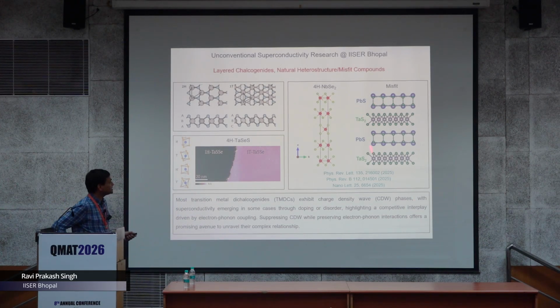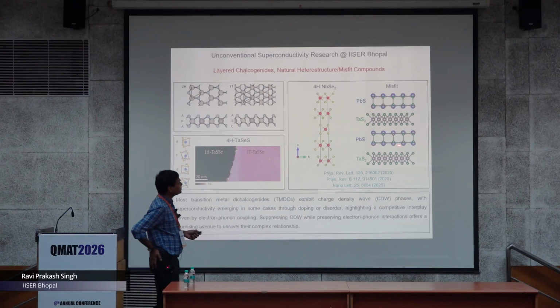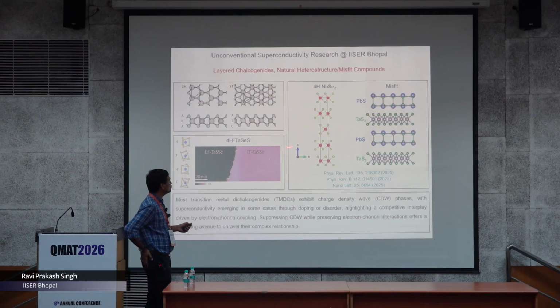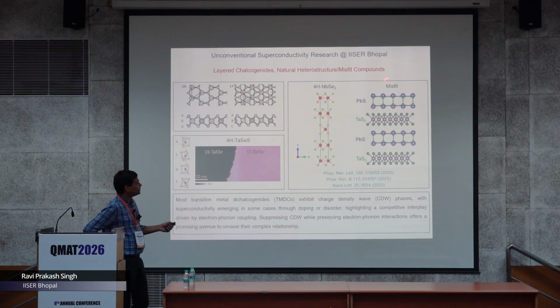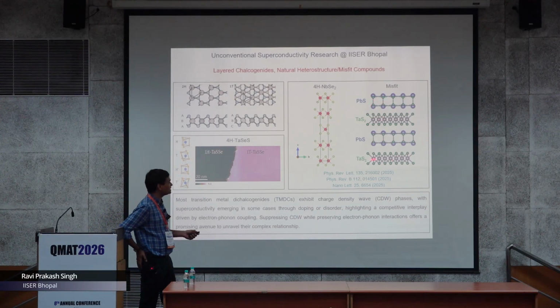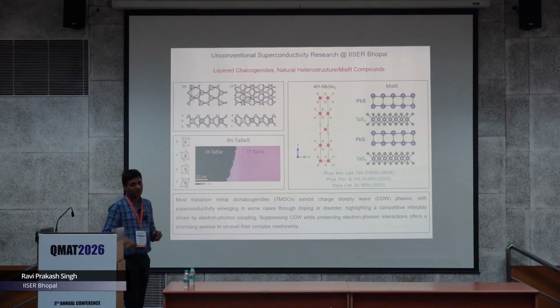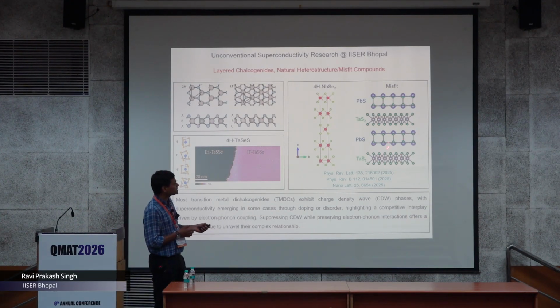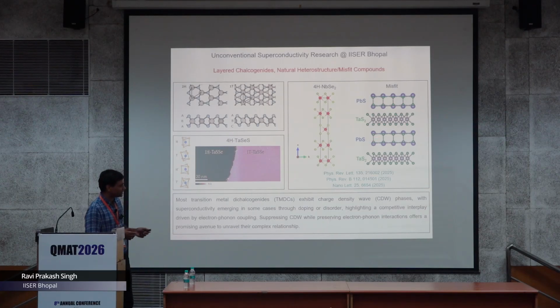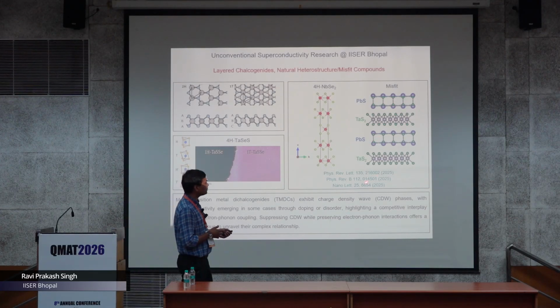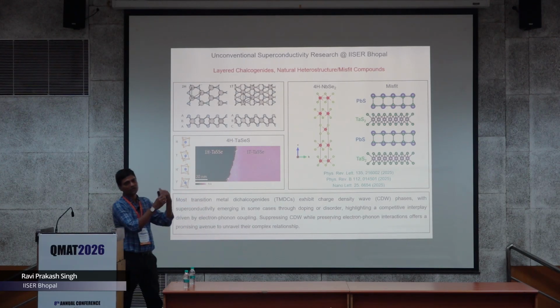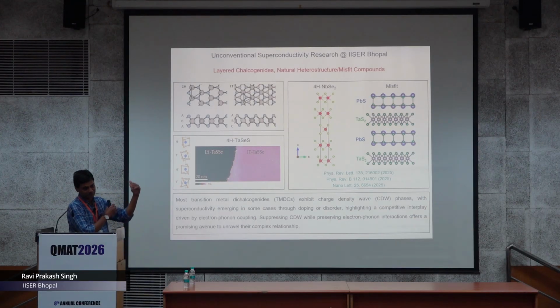Then we are looking at these misfit compounds, and why we are studying them, because in a misfit, instead of doping or anything, you put a spacer layer between these things. And if you look at the electronic structure or ARPES, you will only see the tantalum S2 monolayer property, and you will not see much electron transfer effect from these layers. Otherwise you will get proper monolayer property, 1-to-1 with what you get from mechanical exfoliation.